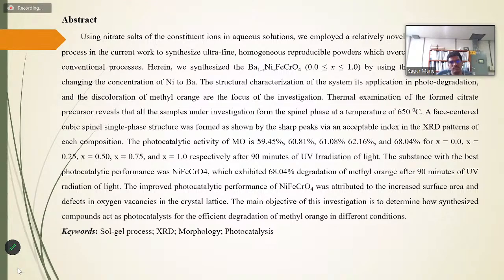Thermal examination of the formed citrate precursor reveals that all the samples under investigation form spinel phase at the temperature range of 650 degrees Celsius. A face-centered cubic spinel structure was well formed, and this is revealed in the XRD pattern. In the photocatalytic activity, we reveal that methyl orange dye is degraded by 59.45, 60.81, 61.08, 62.16, and 68.04 percent for the various compositions of x, and very good photocatalytic activity for x equal to 1.0 after 90 minutes of UV irradiation of the light. The substance with the best photocatalytic performance was NiFeCrO4 and its photocatalytic activity was 68.04.